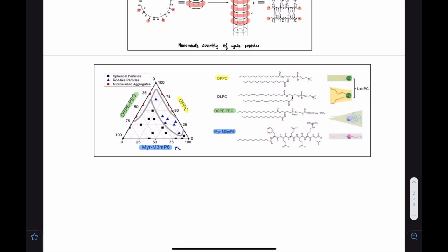In this phase diagram, it is clear that upon introduction of peptide amphiphiles to the lipid mixture, the self-assembly phenomena is enriched significantly. Through the hydrophobic interaction of the alkyl segments and hydrogen bonding among peptide segments, beta sheet structure is more favorable. The amount of the peptide amphiphile plays an important role in deciding the morphological transformation. With more peptide amphiphiles present in the system, rod-like micelles are likely formed, and with a lower amount, the molecules tend to self-assemble into spherical micelles.